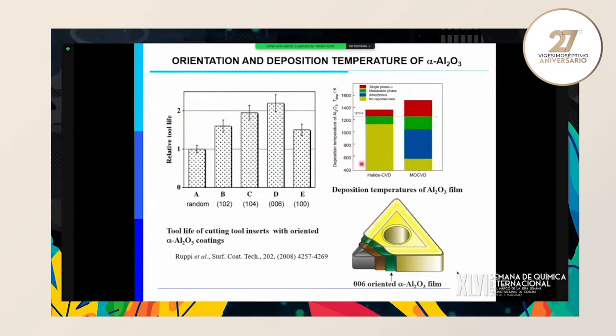And CVD alumina, as I have already talked about, is a very important material for industry. The 006 oriented coating film has the best performance and longest lifetime, and 104 oriented alumina is the most ductile compared with other orientations. Therefore, it is very crucial for cutting tool companies to coat oriented alumina by CVD. In industry, alpha alumina is prepared from aluminum chloride, hydrogen and CO2. Hydrogen is very explosive. Hydrogen chloride is corrosive. If we can make alpha alumina by using a non-explosive, non-corrosive metal organic precursor, it is very useful.